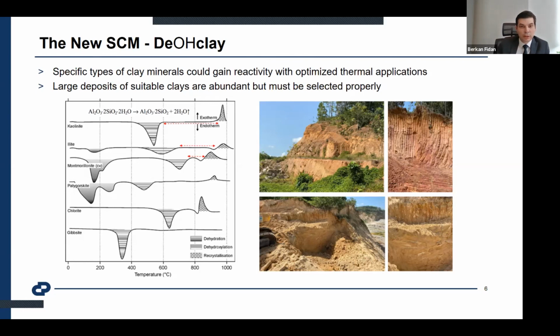And then montmorillonite, but the critical part for montmorillonite is a very narrow range, and the temperatures also increase compared to kaolinite. That means higher heat requirements in that group. And according to that, we checked the abundance and the suitable clays around the targeted regions.